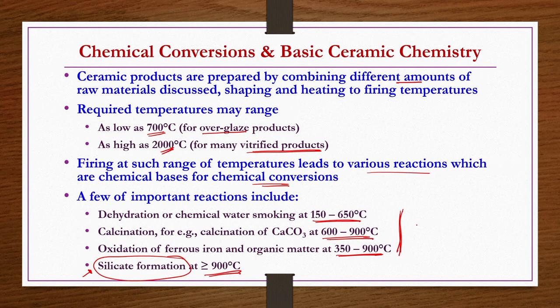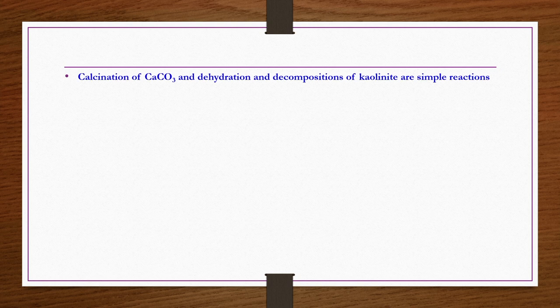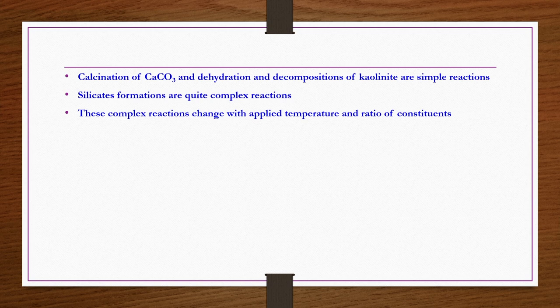And then what you realize here, the dehydration, calcination and oxidation reactions are simple reactions, not much chemistry to understand. But the silicate formation taking place beyond 900 degrees centigrade involves very complex reactions, very difficult to realize, okay. So, calcination of calcium carbonate and dehydration and decomposition of kaolinite are very simple reactions, but silicate formations are quite complex reactions. These complex reactions obviously change with the applied temperature and the constituents of the raw materials taken to prepare a given ceramic product.